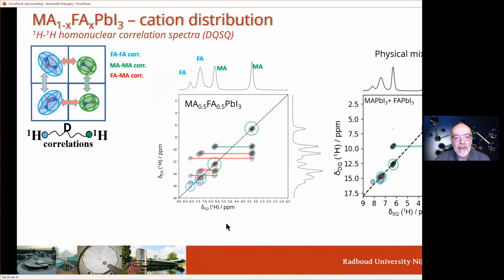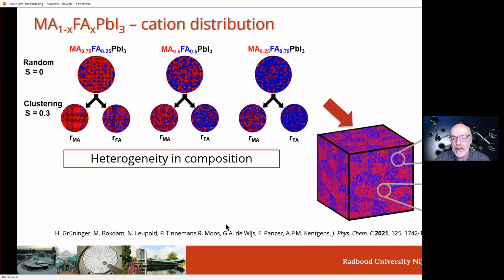Okay, so let's not go into all the details of the spectra, but we figured out that when you have mixed compositions of the cations, there is a certain clustering, that this is not a uniform random distribution of the methylammonium and the so-called formamidinium. We can really figure out that there is a variation in the occurrence of different sites, and essentially the cations like to sit with equal kinds. So methylammoniums like methylammonium neighbors, and formamidiniums like other formamidiniums. So just like people.